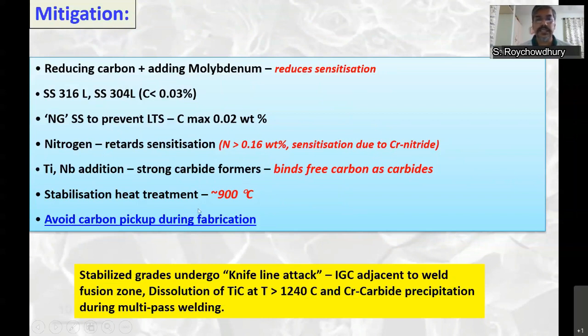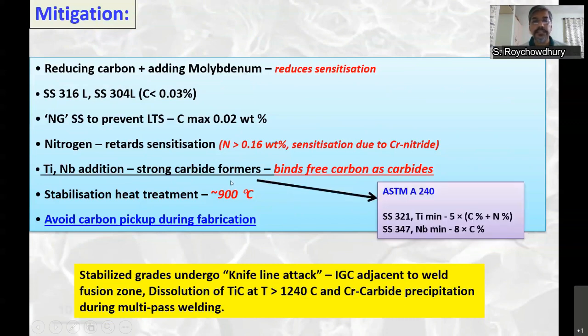But all this stainless steel has to be handled very properly during all stages of fabrication. Why? Because if it is contaminated by grease or any hydrocarbon, and subsequently during welding, these hydrocarbons can break and carbon can be picked up, and all that advantage of low carbon will be lost. So in this stainless steel, these are the stabilized grades where you add this titanium and niobium. This is minimum 5 times carbon plus nitrogen, and minimum 8 times carbon for niobium stabilized steels.